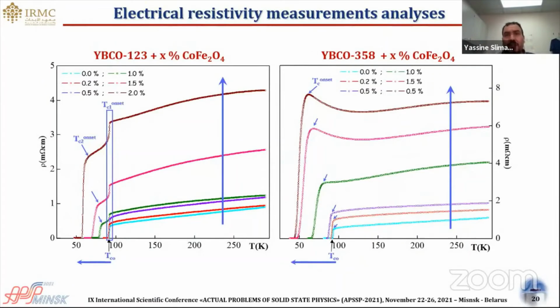Here also we present the electrical resistivity measurements once magnetic nanoparticles are included. In this case, the magnetic nanoparticles provoke a rapid degradation in both intragranular and intergranular properties of the YBCO compound. The magnetic nanoparticles lead also to a reduction in the metallic phase fraction and an increase in the semiconducting phase fraction. So the inclusion of magnetic nanomaterial should definitely reflect that the capacity of transporting high current will be extremely deteriorated.